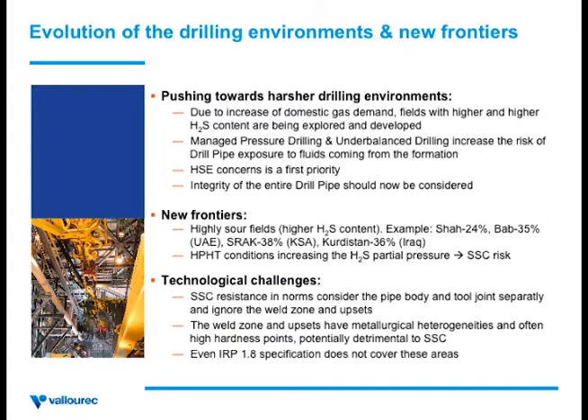One of the main reasons, and it's not only true for sour environments, is that the industry is pushing every limit further, especially with the increased demand for domestic gas in some regions of the world. There are projects being drilled in harsher and harsher environments. First of all, projects that were not economical before due to the very high content of H2S. It's not only an HSE concern and a drilling concern, you also have to deal with the downstream process, H2S as a byproduct, or sulfur as a byproduct. So it's very difficult for operators today to make those projects economical. But the trend is that wells with higher and higher content of H2S, contents that we would not even have believed possible to deal with 10 years ago, are being explored and even developed as we speak.